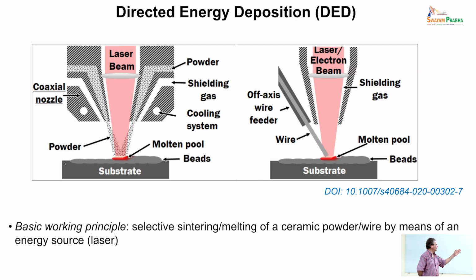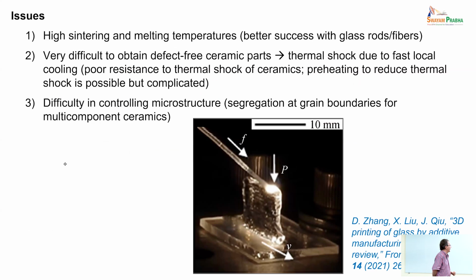And also for ceramic materials, you typically don't have a wire based on a ceramic material where you can do that. Certainly there are also problems in controlling the microstructure. There are some rather successful examples of doing this using silica fibers or silica rods. And silica has a coefficient of thermal expansion of 0.5 × 10^-6 per degree centigrade. So it's virtually zero, it's highly thermal shock resistant. That's why you can locally melt.